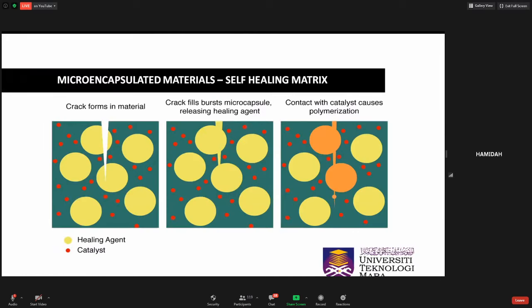Another method of self-healing is by using polymer catalysts. When cracks occur, the microcapsules containing polymer healing agent break and release the healing agent. The healing agent is in contact with catalysts that are also embedded in the materials, causing polymerization and filling up the cracks.